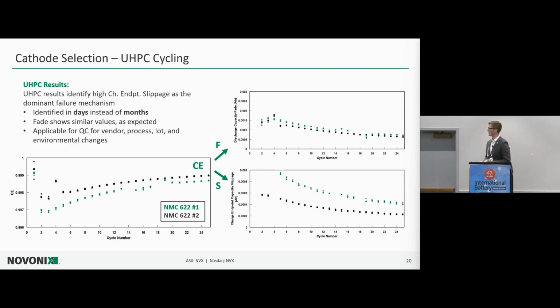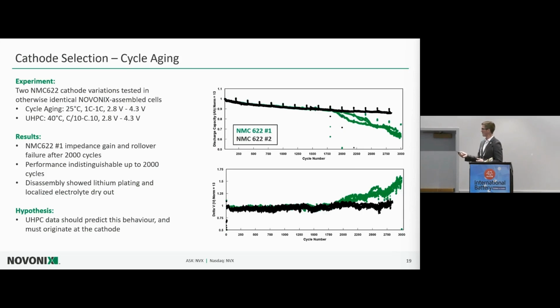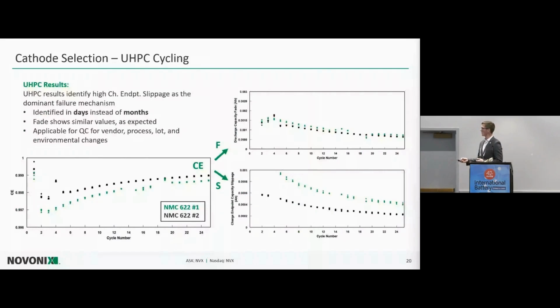So when we look at these results just within a few days, a few early cycles, we can see that this green cell that rolled over very well before the black has much lower coulombic efficiency. These are triplicate cells. This is very repeatable. And really, if we want to understand where this is coming from, we can start splitting up coulombic efficiency into those two terms, that fade-based term, the slippage-based term. And as we would assume, based on what we saw in our long-term cycling, the fade is nearly identical within these short-term experiments. But this slippage-based term is twice as big.